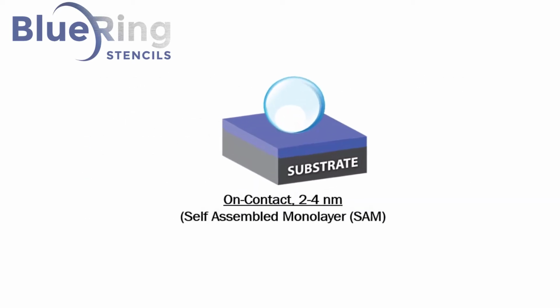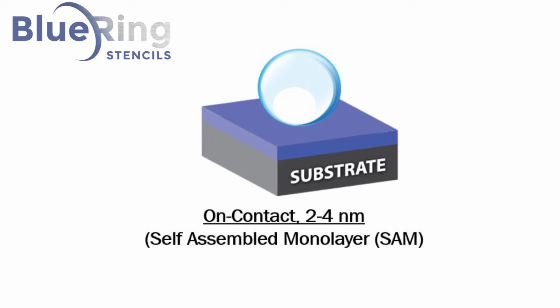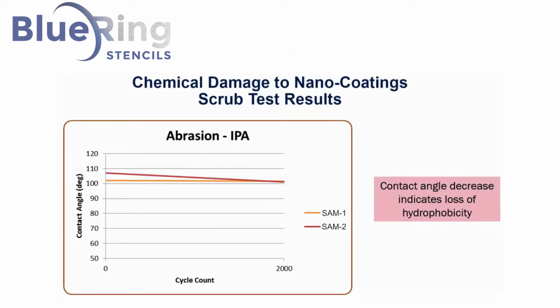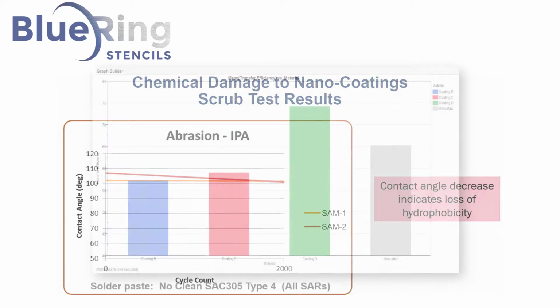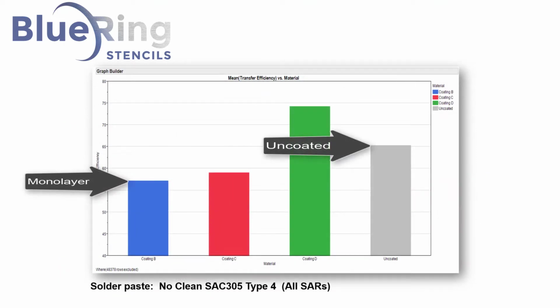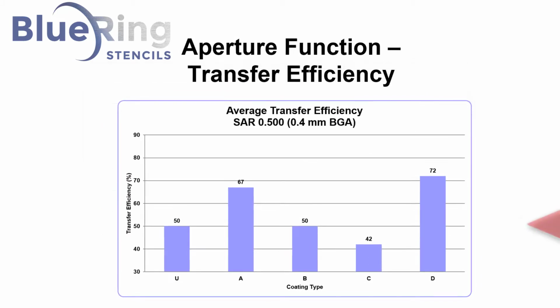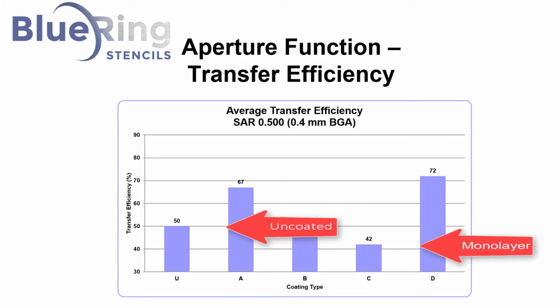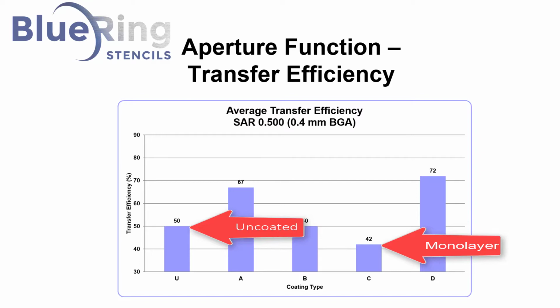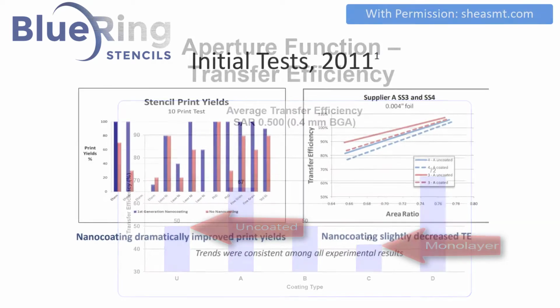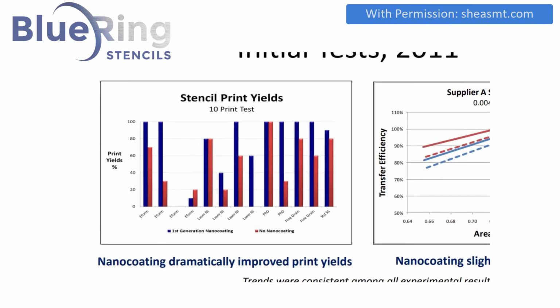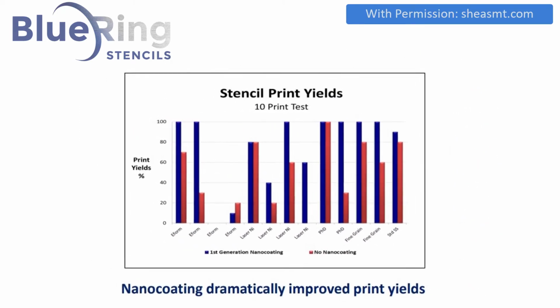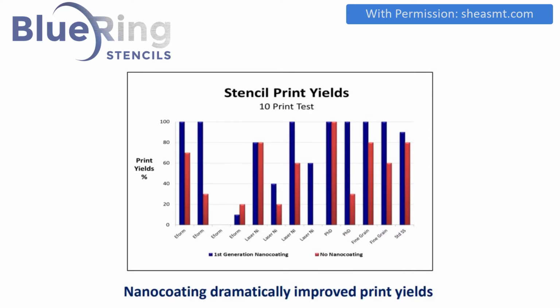However, these initial nanocoating treatments were only nanometers thick. They were clear, and it was difficult to tell when the coating wore off during the production process. This fact was proven time and time again as research done on SMT stencils and nano treatments became public. In fact, several research papers showed a slight decrease in solder paste release or transfer efficiency with these new treatments. Overall, though, the use of these early nano treatments provided better print results than not using them at all and were highly accepted in the marketplace.